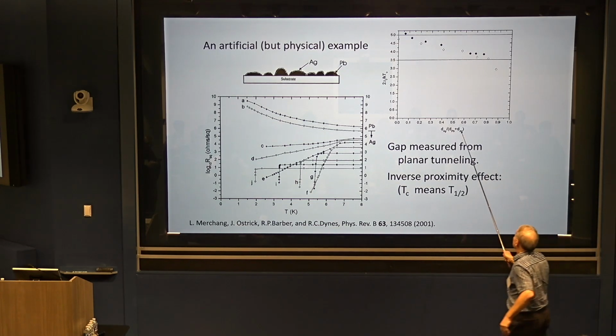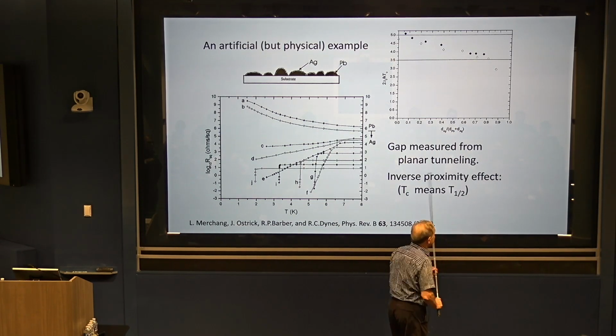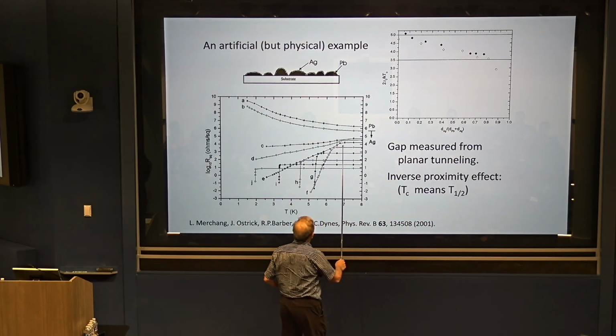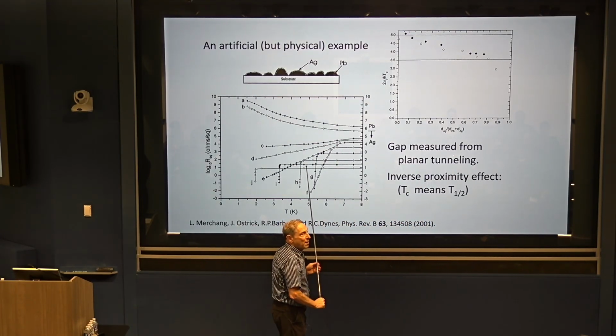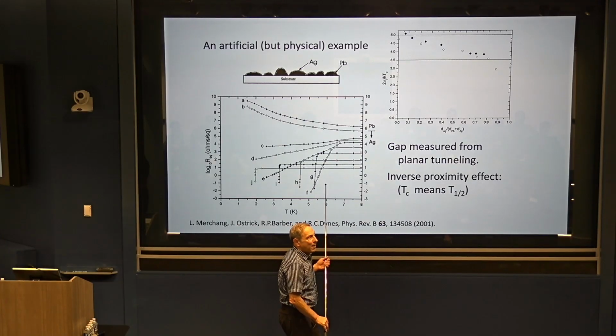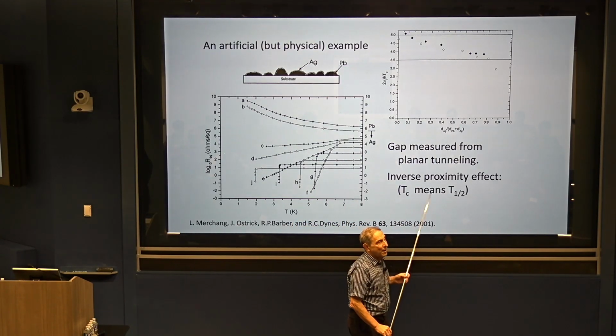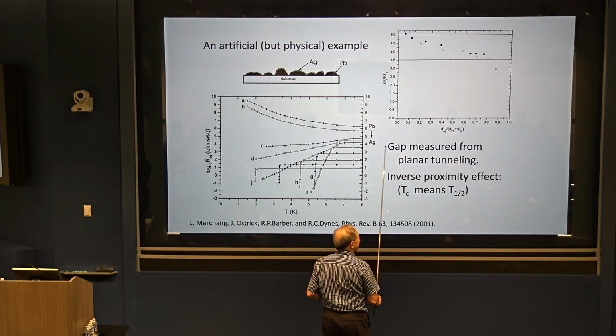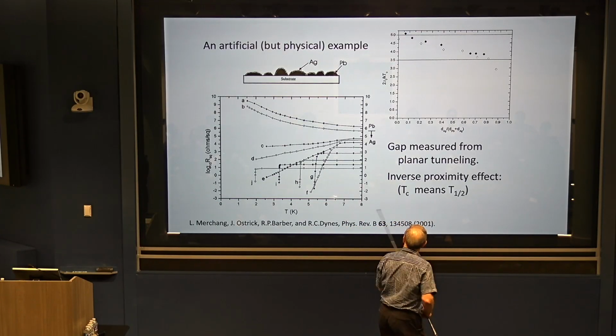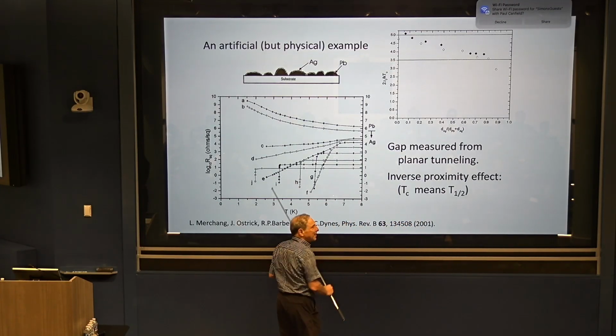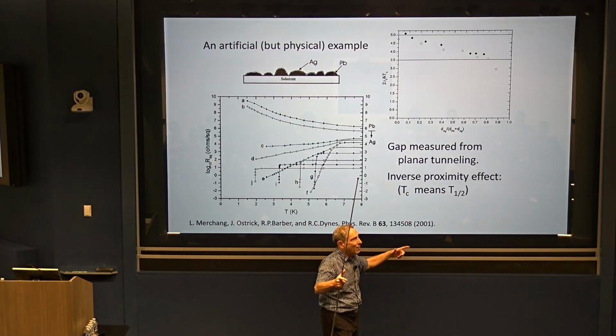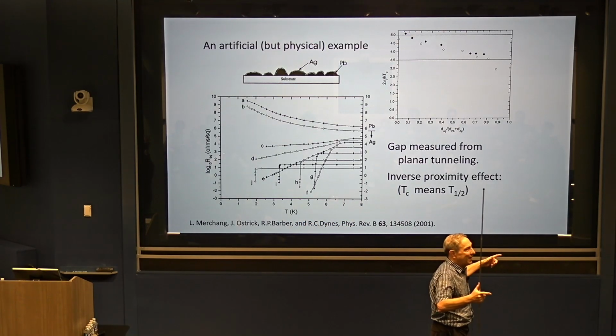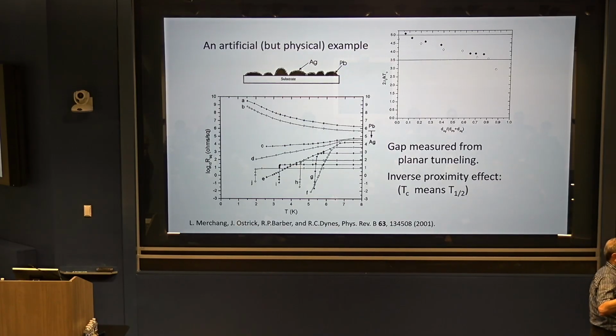So this is only true in the Cooper limit. So this is not happening here. So roughly, it's a self-consistent thing. So when you get a small TC, then your coherence length has gotten larger. If your coherence length is large enough that you're not getting superconductivity within the grain, then you have a uniform superconducting state.